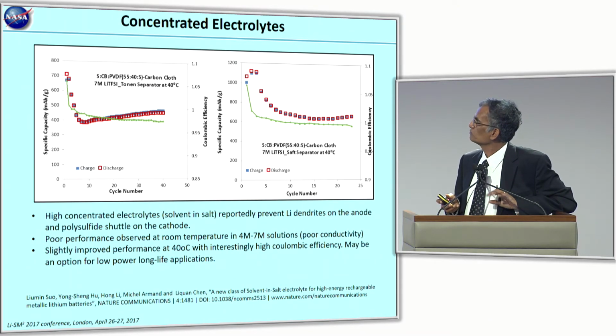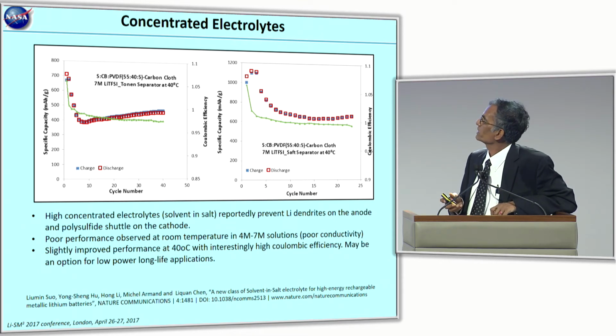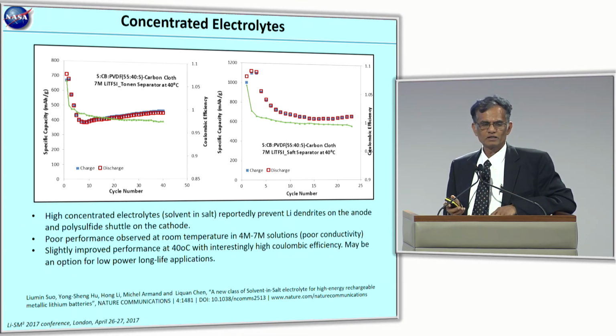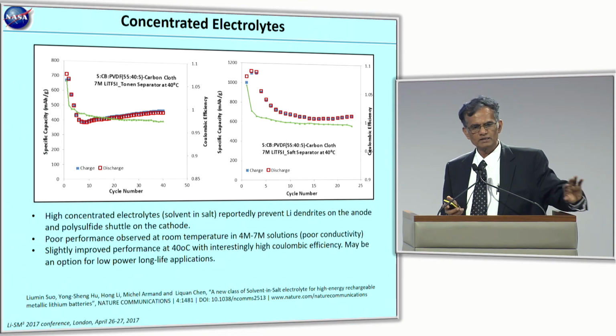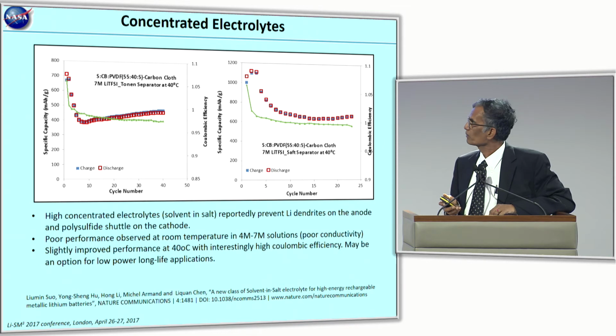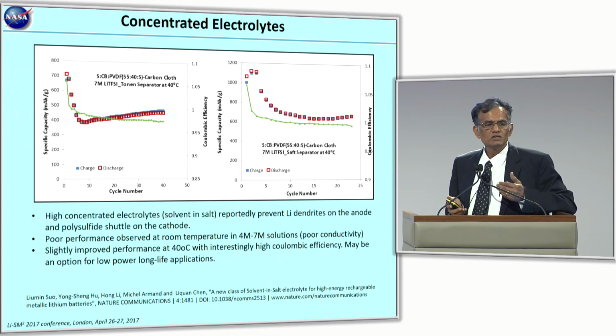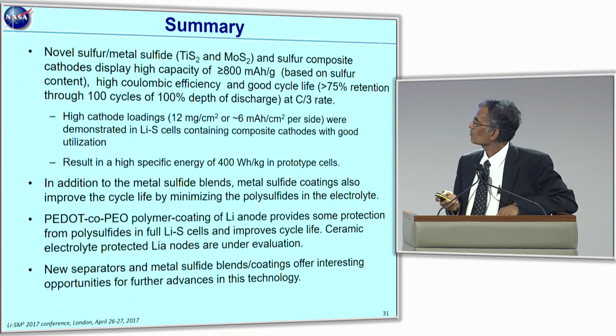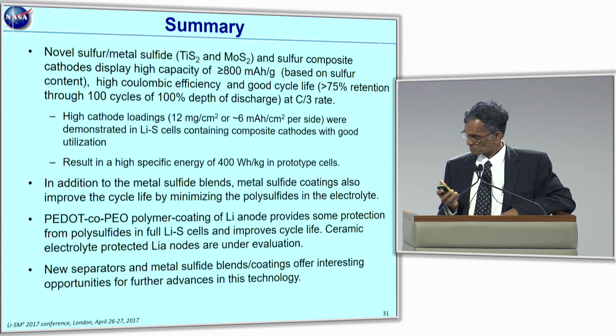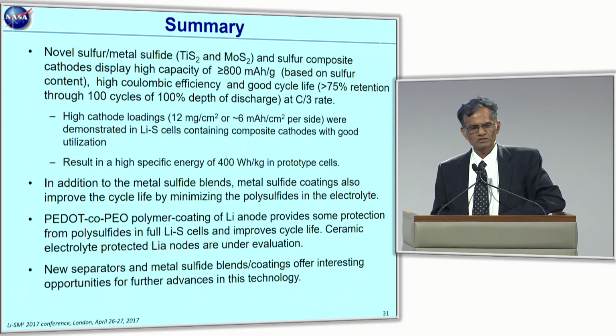And then I would like to finally give another aspect, where Michel Armand and others reported concentrated electrolytes, where both the dendrites and the polysulfides seem to be stopped. They didn't work well at room temperature, but at high temperature they seem to do well at 7 molar concentrations. The interesting thing here is that the Coulombic efficiency is very high, close to 1. So with that, I conclude my talk. There is an interesting direction here in terms of these metal sulfide blends or coatings combined with the ceramic coated separators that we are talking about.